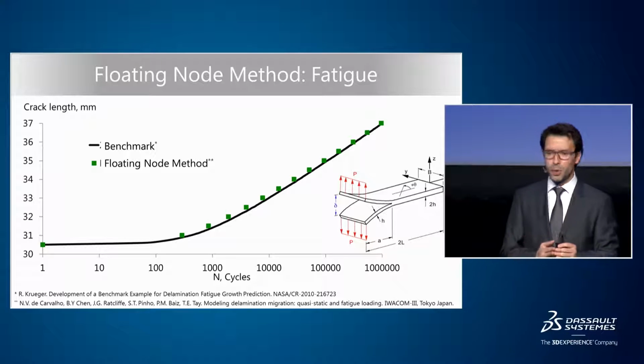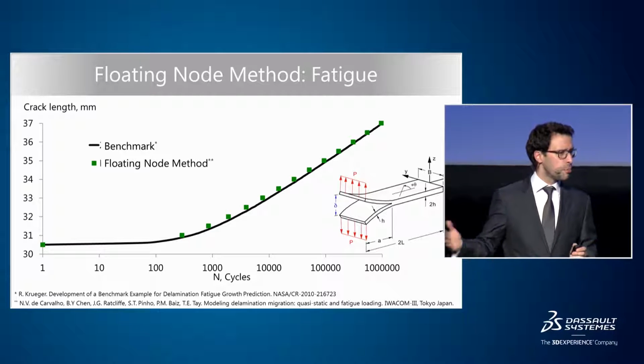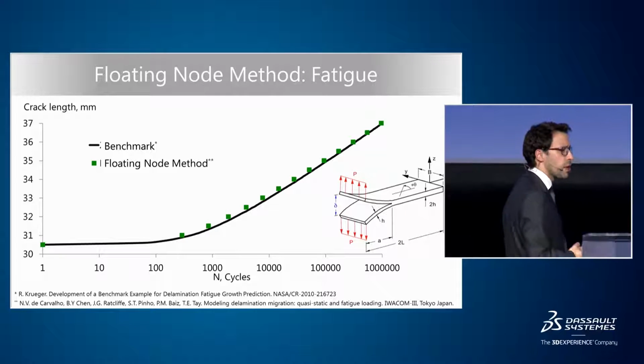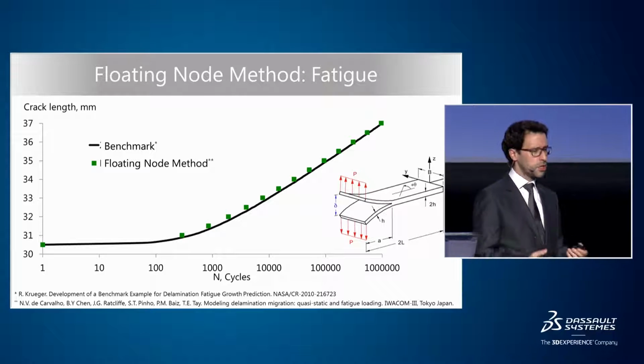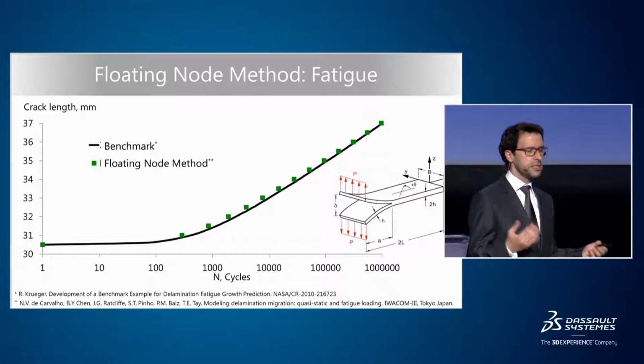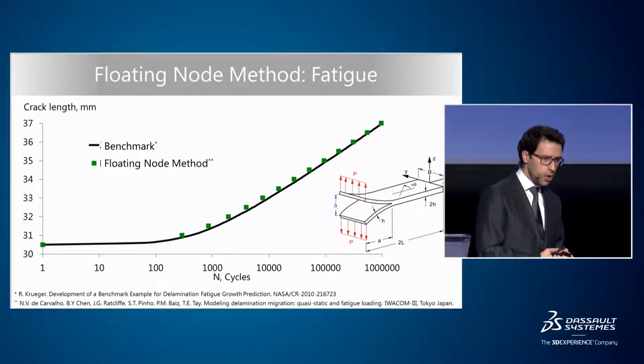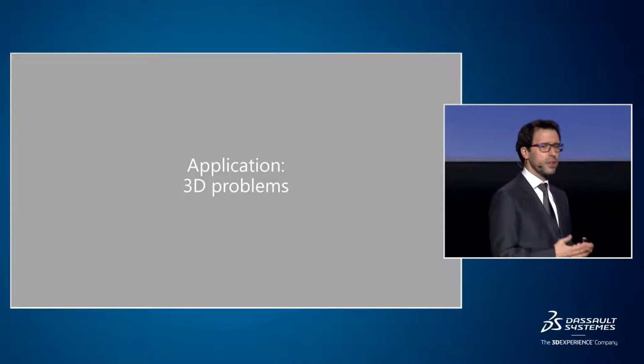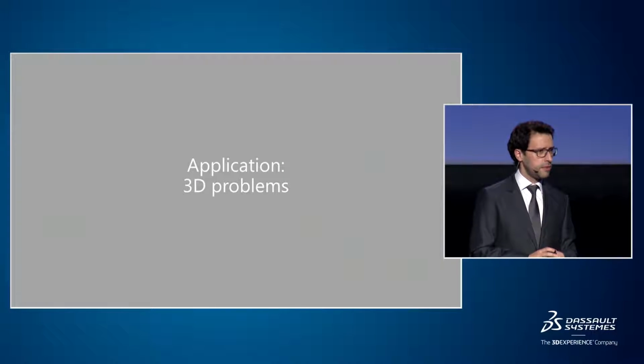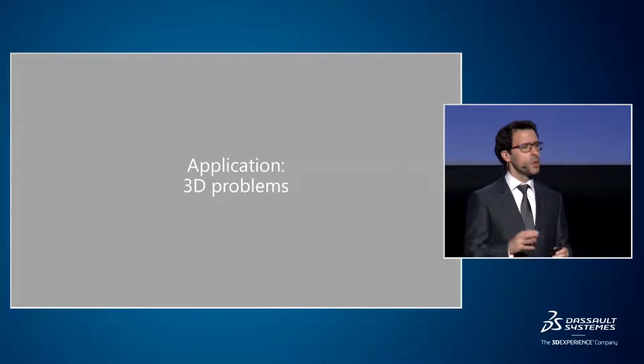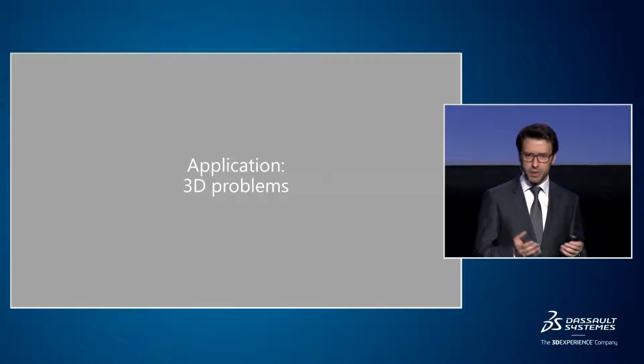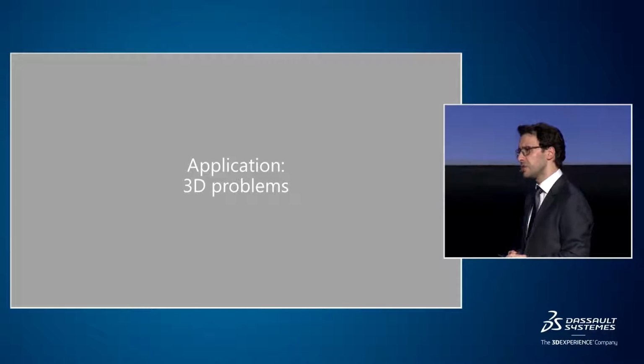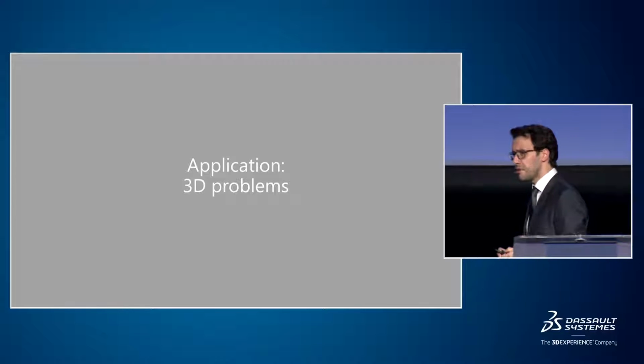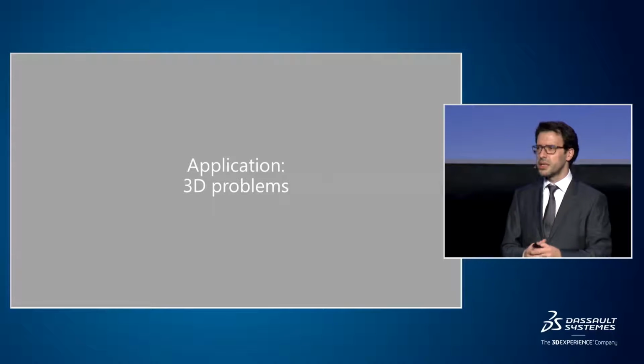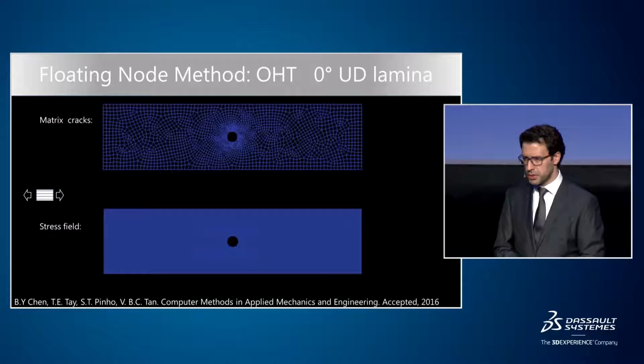So in this plot, I'm showing crack growth as a function of the number of cycles. In black, you have benchmark results. In green, you have the predictions that we got with the floating node method. And as you can see, they agree very well. So all of this is two-dimensional. And for these cases, there are other methods that have existed for some time that could do relatively similar things, with more or less difficulty. But what I'm showing you now is applications in 3 dimensions in which the number of cracks that we are simulating makes it very difficult for any other methods to replicate.